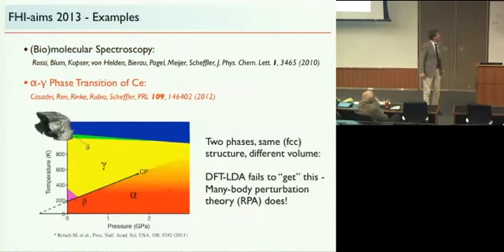We can go to the other end of the periodic table and look at something like cerium. Now, cerium is interesting to get right if you're interested in catalysis, but it also has some fundamentally interesting aspects like this phase diagram here, temperature and pressure, of just bulk cerium. And you see a bunch of phases, and in particular this alpha and gamma here, which are structurally identical, except that if you go down in temperature, at some point the volume simply collapses into a different phase. And this volume collapse is one of the cases where traditional density functional theory, for instance in the local density approximation, simply fails. They get one phase but not the other. But it turns out, as shown in this paper here, that if you use a many-body perturbation method a little bit higher on this fifth rung of the ladder that I showed before, you actually get this transition.